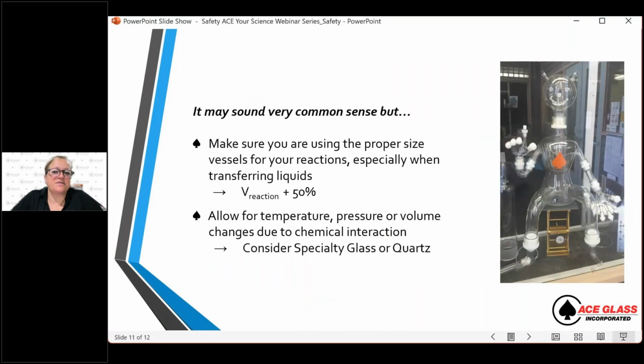All right, I know it sounds very common sense, but we actually see this more often than you would believe. It is very important that you use a proper vessel size for your reaction. Most of you probably go, well, duh, right? But if you know you're going to have an overall reaction volume in the end of like 4 liters, use at least a 6-liter vessel, right? So the rule of thumb is to take the volume of your reaction and add 50% for your container so that you have adequate room should there be any kind of foaming or bubbling, any kind of liquid expansion that you didn't expect, any kind of gas formation that causes it to go up. So just keep these things in mind.